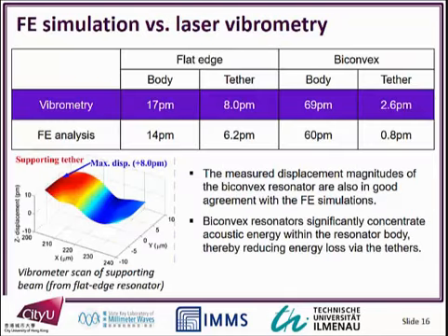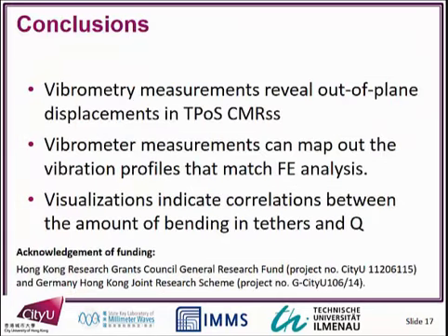To summarize all of this data together, the amount of displacement you're seeing is pretty much comparable to what we're seeing in the FE analysis. So this method does seem to be able to map out what we see in FE. Until this point, there was no way of experimentally verifying whether these FE simulations are indeed true. In conclusion, these vibrometry measurements reveal out-of-plane displacements in the TPoS CMRs, and they can map out, as I've shown, these vibration profiles that match the FE analysis. These visualizations also indicate some correlation between the amount of bending displacement in the deformation of the tether supports and the measured quality factor.